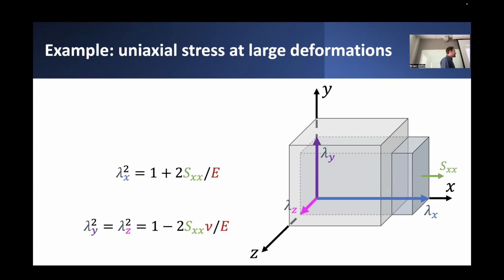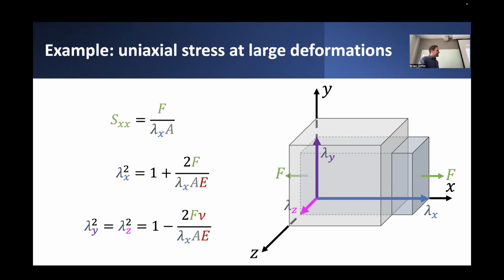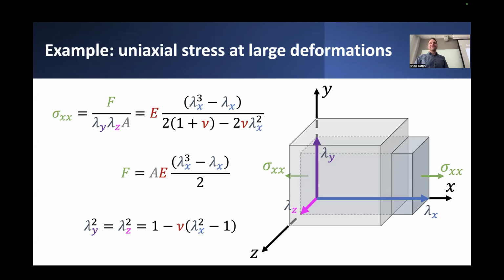We've actually come up with a relationship between stretch ratio, or the amount by which each of these different edges of this cube are elongating, and we related it to the applied stress, the second Piola-Kirchhoff stress, in the axial direction. The only thing that we have to do now is remember how we defined second Piola-Kirchhoff stress. It was total applied force divided by initial area, and then to do that extra transformation, we had to divide by the axial stretch ratio. We can plug that into these relationships and move things around slightly until eventually what we get is this.